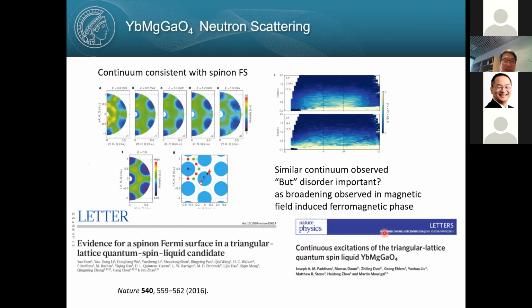And at that low temperature, they measured magnetic excitation. This is the magnetic excitation at different energies, and you immediately notice this excitation is broad, extended over Q space. It doesn't look like a line expected for magnon excitation. They say this broad excitation extending over Q space and energy is a continuum excitation. And they assume a Fermi surface of spinons like this, and they say they can account for this pattern quite reasonably. Therefore this is evidence for a spinon Fermi surface.